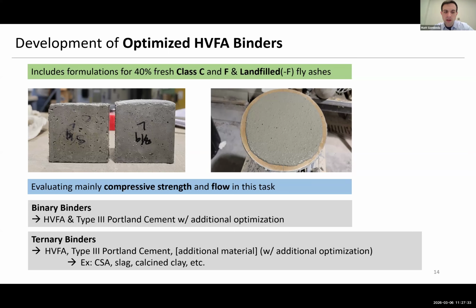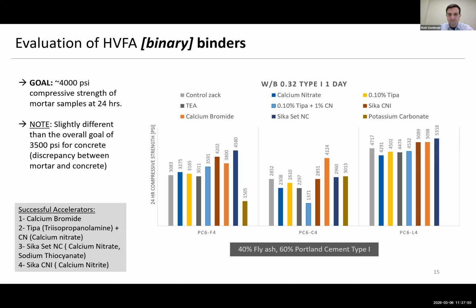We looked at binary binders, but just the type 3, because back in 2020, 1L was still not really the common thing on the market yet. So it was mostly type 3 and the high volume fly ash. And we also did some ternary ones, which actually didn't seem as promising. And we moved forward with the binary options.